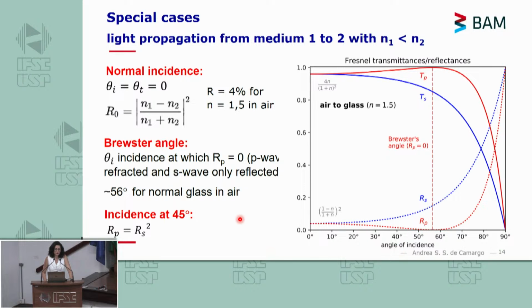We have some special cases to look at here. One of them is light propagation from medium 1 to 2 when n1 is smaller than n2, right? So air to glass, for example. If we do normal incidence, that means θi equals 0. So with normal incidence, most of the light will be transmitted, okay? And only 4% will be reflected, as you can see here, for a refractive index of 1.5 of the material. Of course, this will depend on the refractive index, but most of the light will be transmitted, both in S and P polarization, as you can see in this graphic here, right? So at angle 0, maximum TP and TS, and minimum RS and RP.